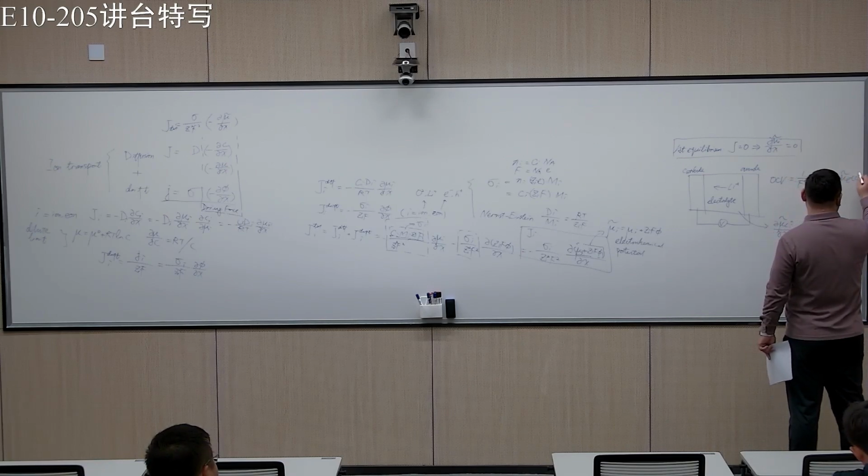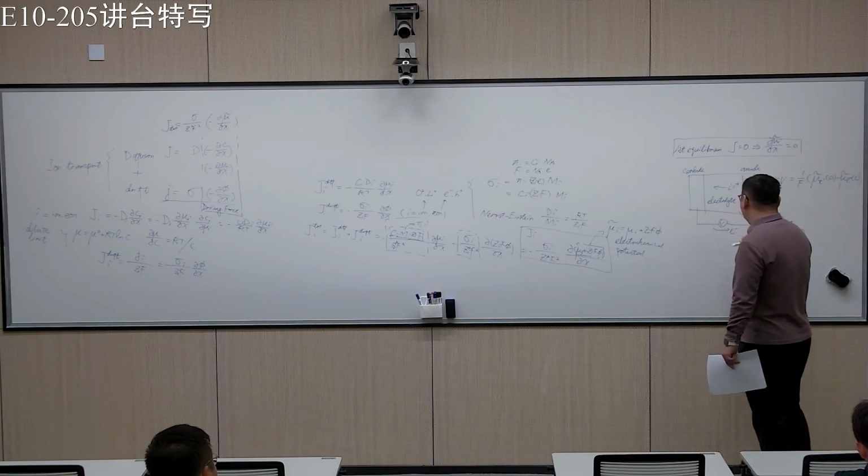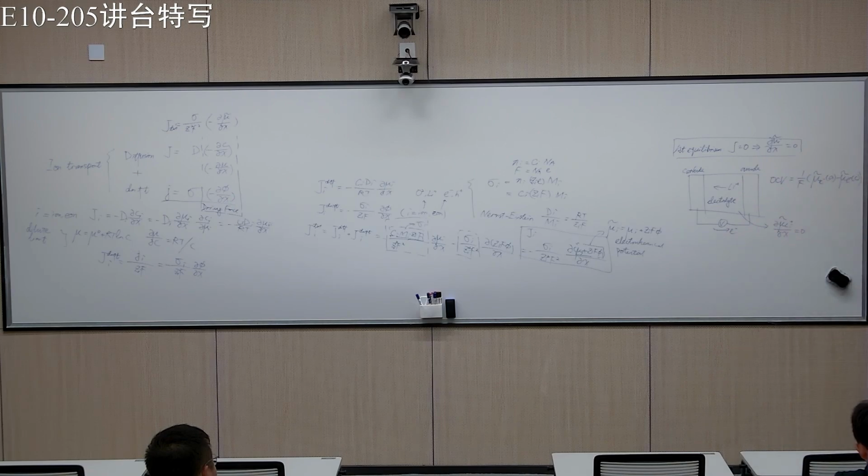Okay. So this is because that's how we measure, right? We use a multimeter to measure between the cathode and anode. So basically, if we have the electron flow through the multimeter, it is the difference between the electrochemical potential of electrons which serves as a driving force, right? So that's why the OCV is directly linked to the difference in the electrochemical potential of electrons.